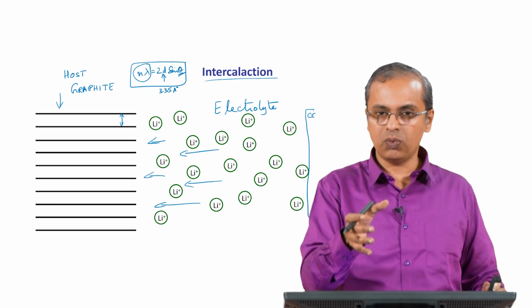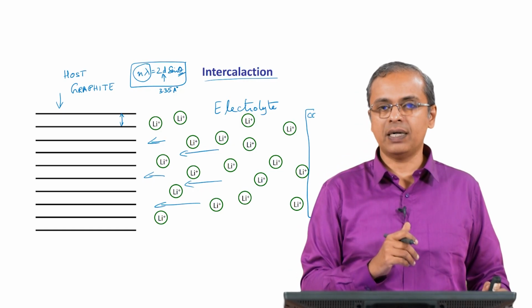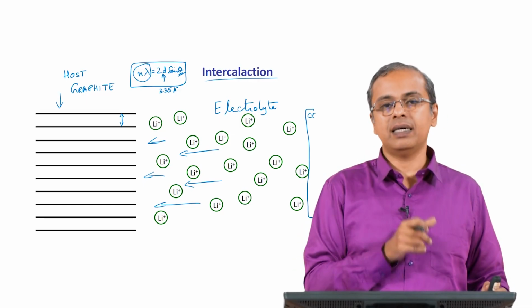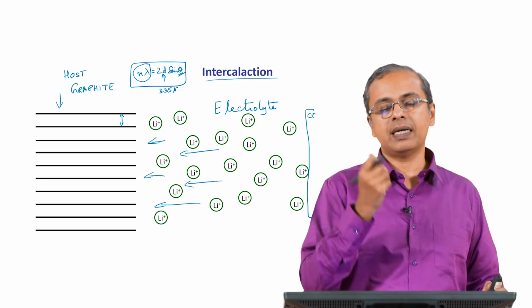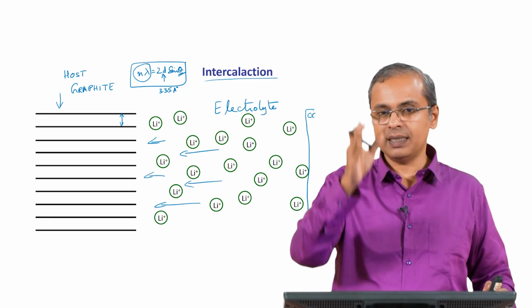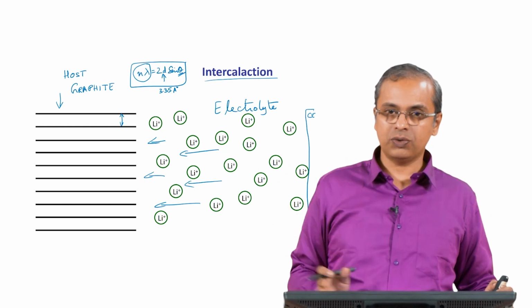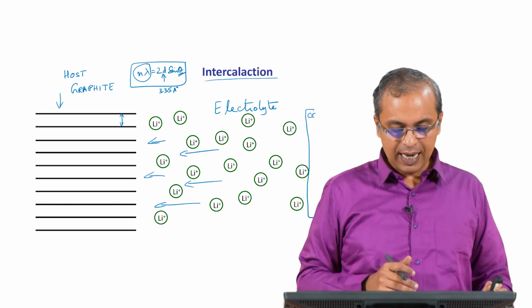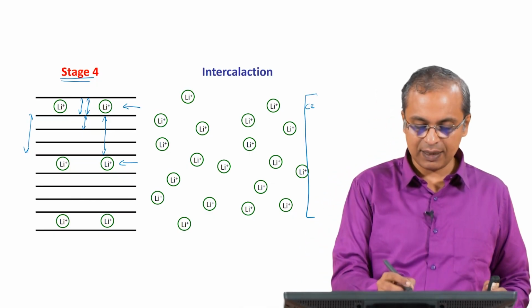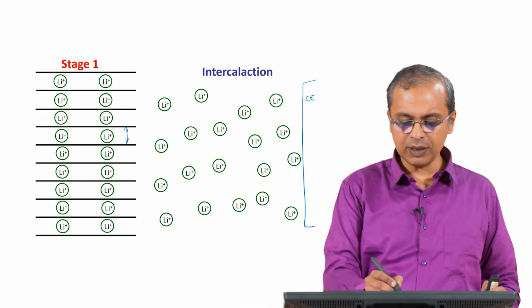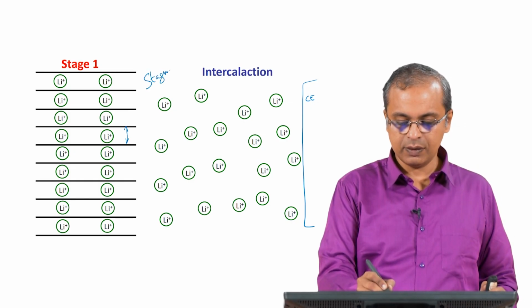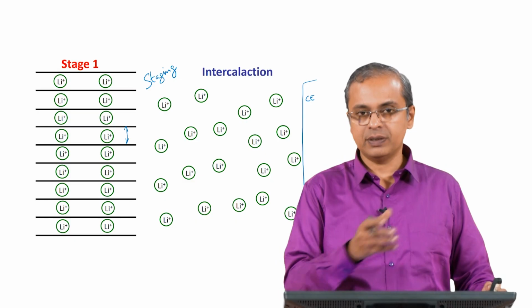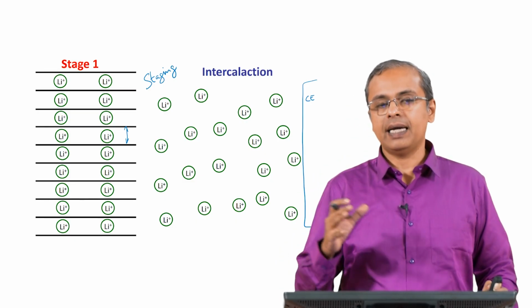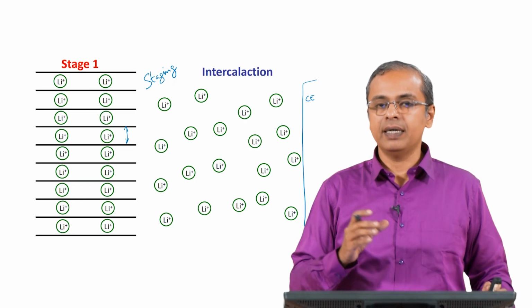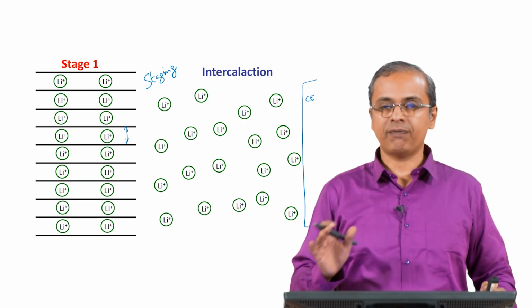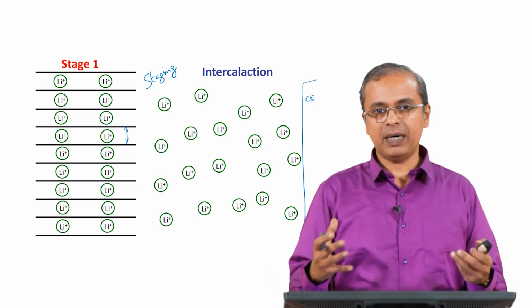You can do an in situ X-ray diffraction kind of experiment, where you have the lithium cell inside the X-ray setup, and you can run the cell, and then you can see the (002) peak steadily shifting to lower and lower values of theta. So, that is what happens, and this idea that it happens in stages is referred to as staging. Intercalation happens through this process of staging in graphite, and it helps secure the lithium in a safe way, and it helps create a situation where the lithium ion battery can function safely. That is, I think, a very key part of this whole lithium ion technology.